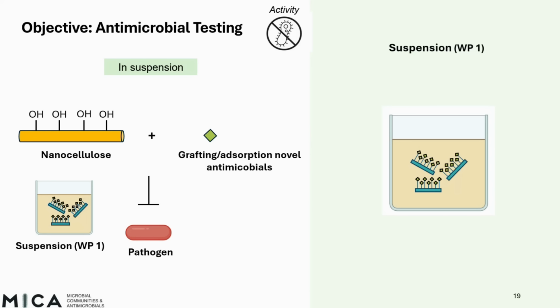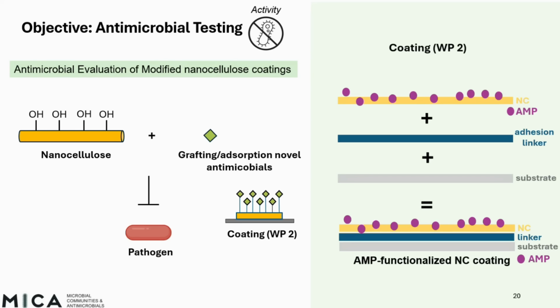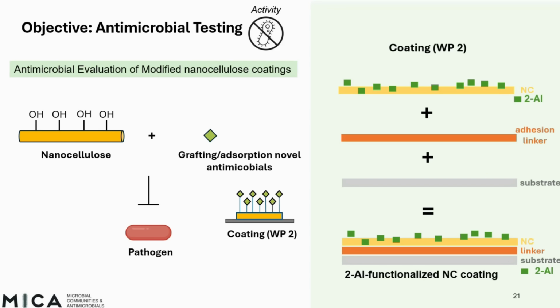So first, to functionalize this nanocellulose, we modify it and test for its activity in suspension. And then we test the modified nanocellulose on coated substrates and see how it inhibits potential pathogens present on high traffic surfaces. So first we have the substrate, then we have the adhesion linker, and then we have the modified nanocellulose in order to form, in this case, the AMP functionalized nanocellulose coating, and also the same to have the 2AI functionalized nanocellulose coating.